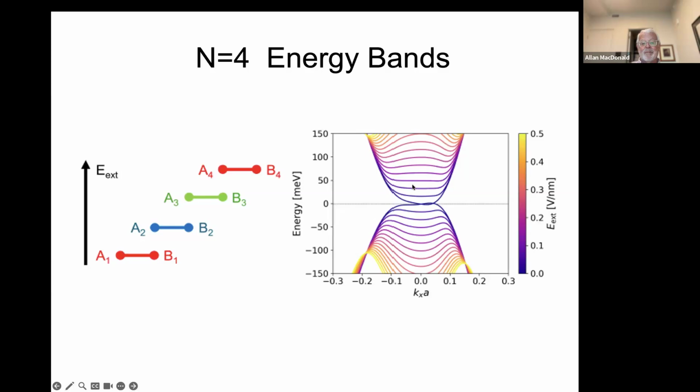And so if you look at some typical plot, and this plot is some band structure model many of you are familiar with, that also includes other smaller effects I haven't pointed to. And you can see here that the bands are very flat because they disperse with a high power of k for many layers, because it requires repeated hopping between the layers to get from one side to the other.